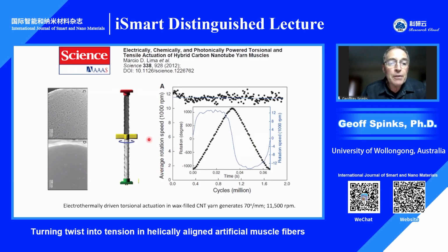But by filling up the carbon nanotube yarns with a paraffin wax, they were able to use thermal expansion of the wax to cause the yarn volume to increase, and that also produced a torsional actuation. So with a simple fabrication process, they were able to produce completely dry actuators that operate outside the beaker.